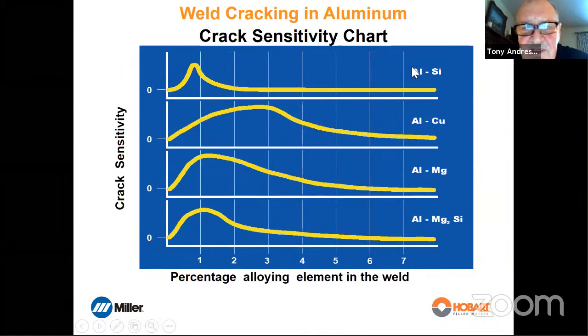So if we look at the top one here, aluminum and silicon, we can see, and I'll tell you, at 0.8%, just below 1%, 0.8% is the peak crack sensitivity of silicon in aluminum. So if you've got a piece of aluminum and you've got 0.8% silicon and you try welding it, chances are it's going to crack, right? Now, with copper, it ranges all the way from just above 1 all the way over here to about here, peaks around here. So anywhere between 1.5 to 3.5, you could run into crack sensitivity problems. So the copper alloys tend to have a wide range of crack sensitivity, and for that reason, sometimes somewhat difficult to weld. Aluminum magnesium peaks at around 1, just above 1%. Magnesium silicide, again, just around 1, just over 1%.